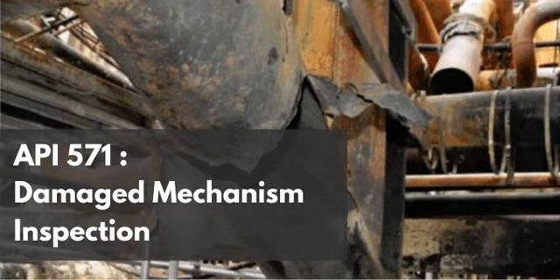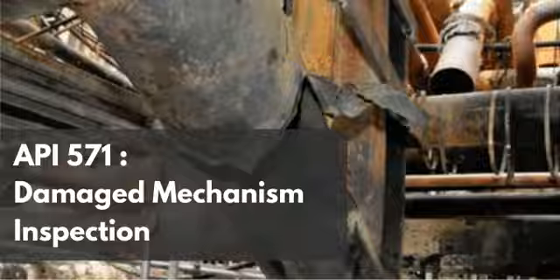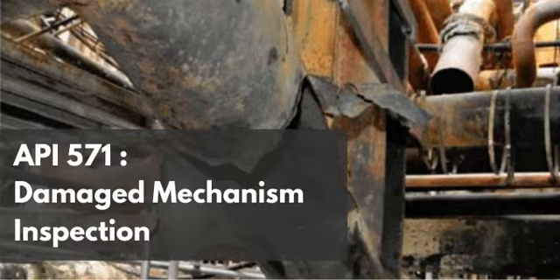That is the core mechanical dynamic driving the severity of the damage. Let's think about what is happening on the surface of the steel. Even in a corrosive environment, iron will try to react with the sulfur or carbon in the stream to form a very weak, very thin semi-protective scale, like an iron sulfide or iron carbonate film. Right. If you have a slow, smooth, laminar flow of a corrosive degraded amine, it gently interacts with that surface. It slowly dissolves that weak scale and evenly removes layers of the steel across a large, widespread area. So it's a slow wash. Exactly. But the moment you introduce high velocity or turbulence, say, the fluid hits a sharp 90-degree elbow in the piping, or passes through a reduction in pipe diameter, or crashes against a weld root sticking out into the flow stream, you completely disrupt that smooth flow.